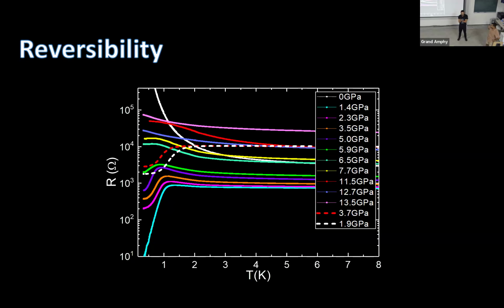Nevertheless, we are doing experiments now on niobium thin films, and in this sample we managed to go back and see the same behavior. So indium oxide is one thing and niobium is the other thing, but in niobium we do see this reversibility very well.